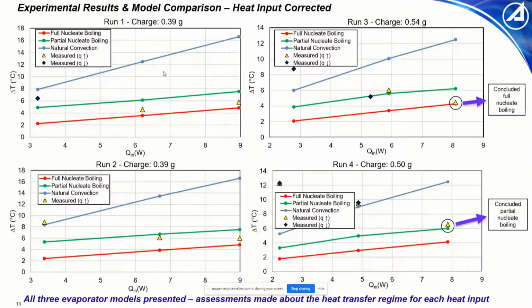We can tell by the trend of the experimental data that as heat input increases, we see a sharp drop in the measured temperature drop, indicating that at low heat input values, nucleate boiling had not been initiated. As heat flux increased, gradually boiling initiated, so we shift from a natural convection model to a partial nucleate boiling model, and at high heat fluxes, typically to a full nucleate boiling model.